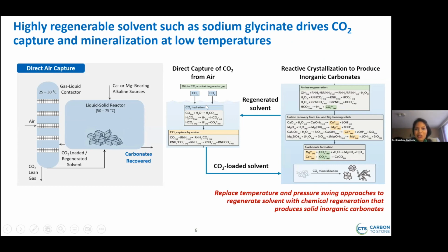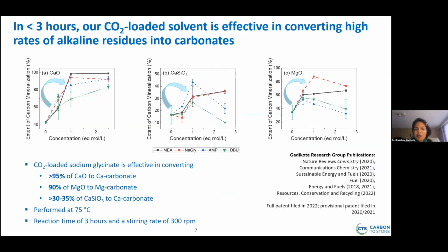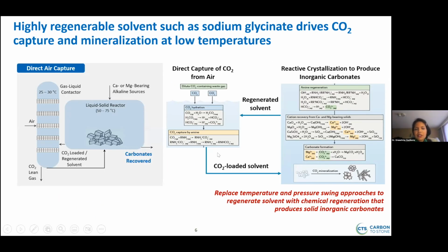So to walk you through some chemistry here, and I'm a chemical engineer by training, so I need to show you some chemical reactions so I can actually sleep better at night. So here's the chemistry for the direct air capture of CO2. If we do not have a solvent in the system, we effectively dissolve the CO2 in the aqueous phase. And then once we add the solvent to the system, we're able to form either a carbamate or a bicarbonate-rich solution. What we can then do is transfer the CO2-loaded solvent over to a liquid solid reactor. And into that reactor, we put in the alkaline resources. These alkaline resources react with the CO2-loaded solvents to produce solid carbonates. And in the process of doing that, the solvent actually gets regenerated. And so now we're able to loop the solvent back in for more CO2 capture from air. So effectively, this process replaces conventional temperature and pressure-based swing strategies for producing high purity CO2.